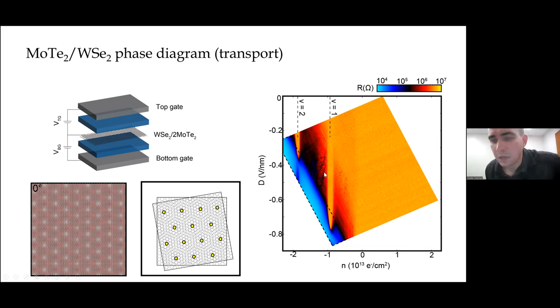And that's just a point that's worth remembering in the context of realizing these systems at higher energy scale, right? So this is not a system in which we've minimized the bandwidth in order to realize some very fragile state at low temperature. It's a system that has a fairly large exchange gap driven by fairly strong interactions, and in that sense is not particularly a flat band phenomenon.